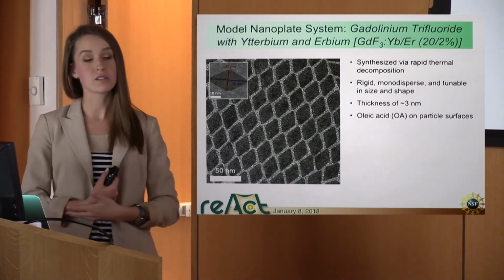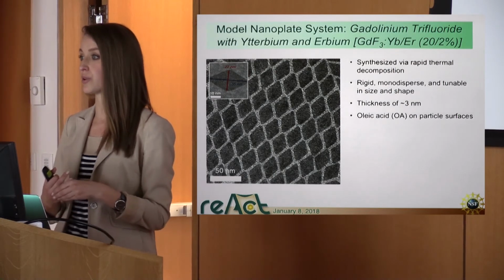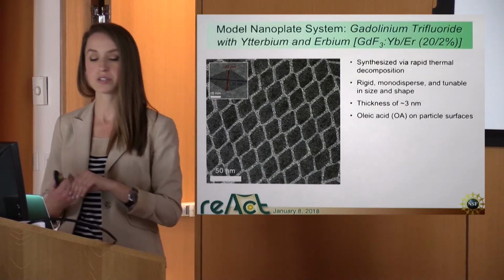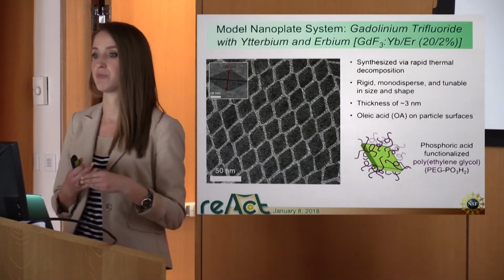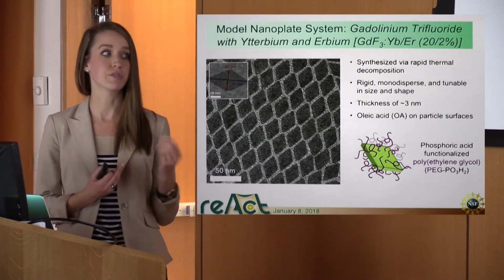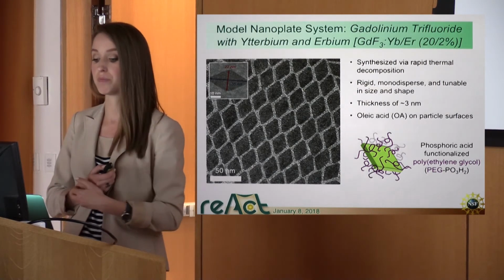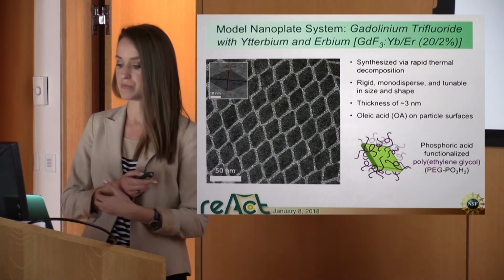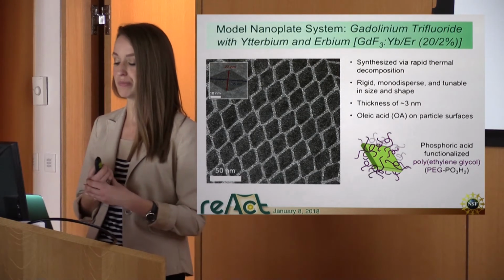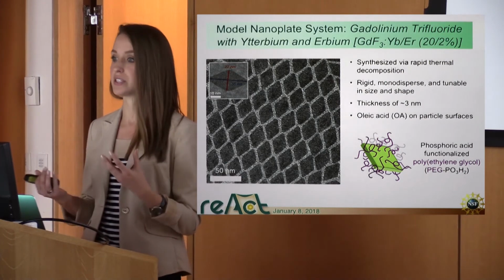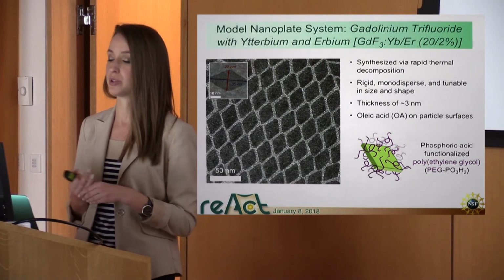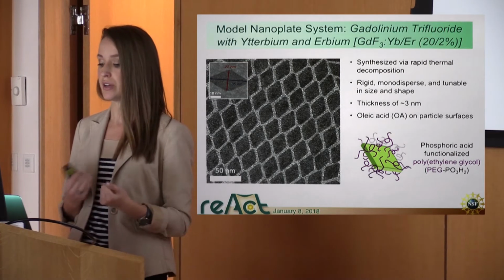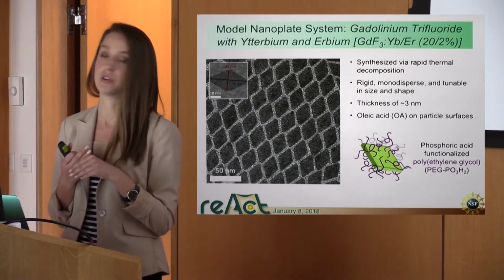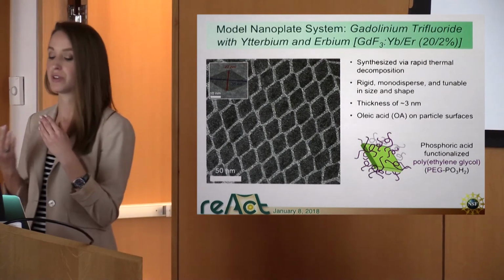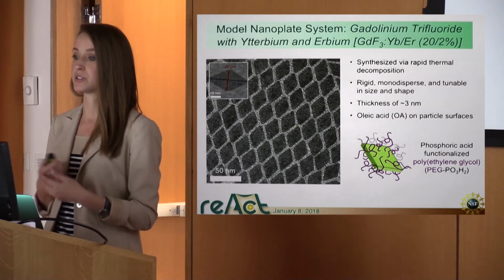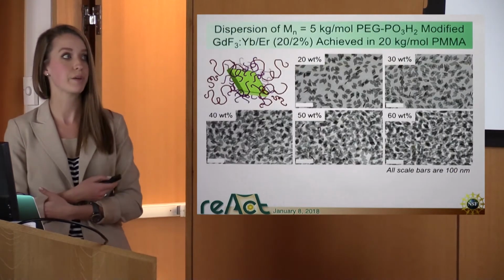As synthesized, these have oleic acid on the surface. So in order to incorporate them into a polymer matrix, I've changed the surface chemistry of my particles through a ligand exchange to functionalize these particles with PEG, polyethylene glycol. And this is an ideal system in that now I've designed a particle that actually has a favorable attraction to one of my blocks. In an undercooled melt, PEG and PMMA have an enthalpically attractive interaction, so I can disperse these particles quite well in PMMA.